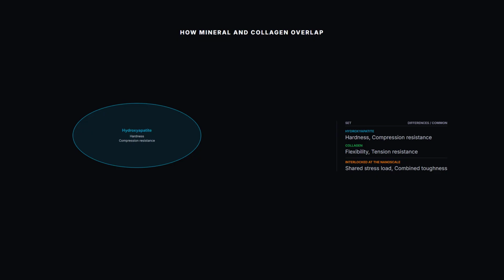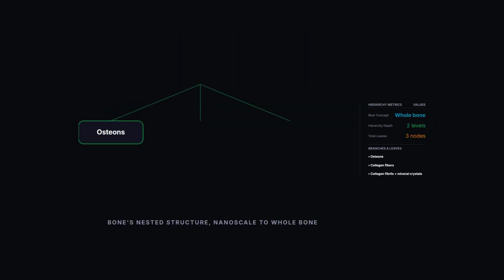Here's the part that actually explains the toughness. Mineral and collagen aren't just mixed together. They're mechanically interlocked at the nanoscale, with hydroxyapatite crystals embedded directly inside and around the collagen fibers. That intimate overlap is what lets stress get shared between a stiff component and a flexible one instead of concentrating in just one. Zoom out far enough, and bone structure looks like a set of nested building blocks, each scale adding its own trick for handling stress.